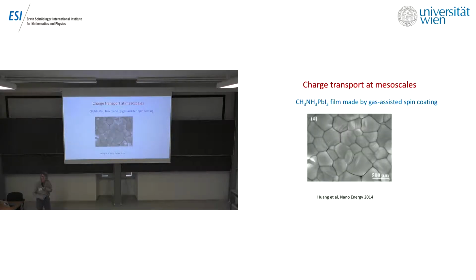Now, coming back to our picture of the beach, this isn't a picture of a beach, this is a picture of a perovskite, and they're very multicrystalline. So you will have seen in Jarvis' talk that he predicts these very high mobilities. And one reason why the mobility is so much higher than experiment, we're talking about 1 or 2 orders of magnitude here, is because the perovskites are polycrystalline on a length scale, on this mesoscale of tens to hundreds of nanometers.